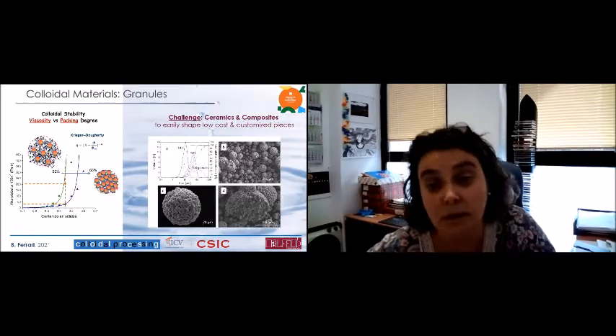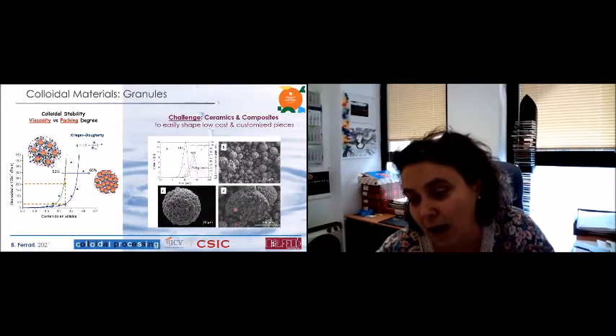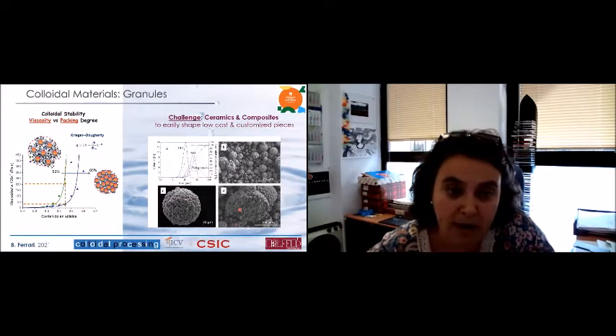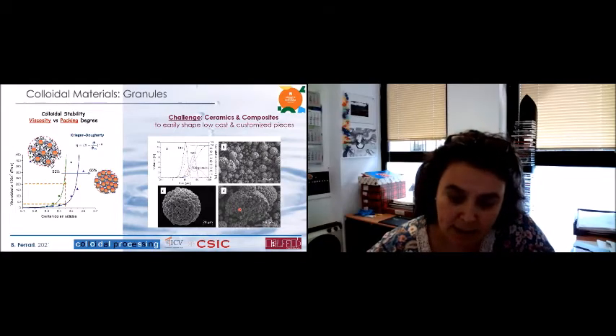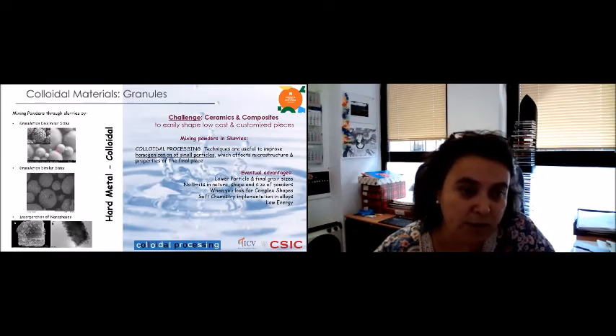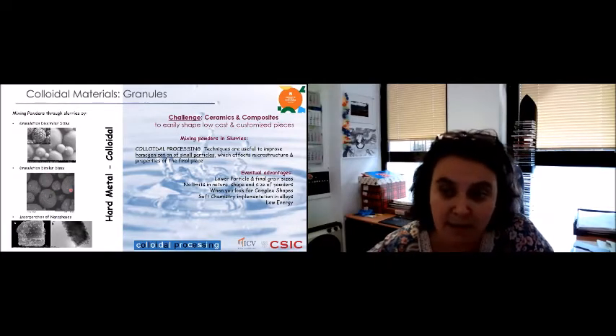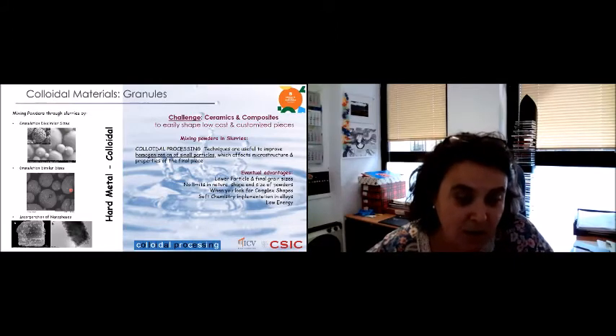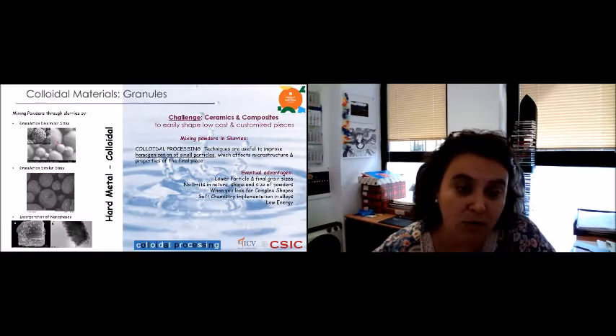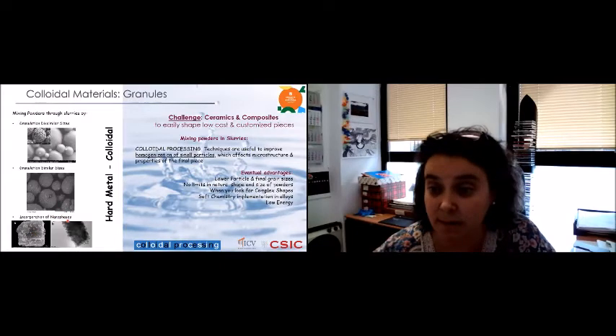And this is very important also to granulate. We need to have full dense granules to make the spray drying and bed process work, right? So also in granules, you can manage different granules with different sizes. You see here titanium surrounded by alumina, or even you can play with particles with similar phases, similar sizes, right? And also you can incorporate into a big granule some nanophases by synthesis, right?